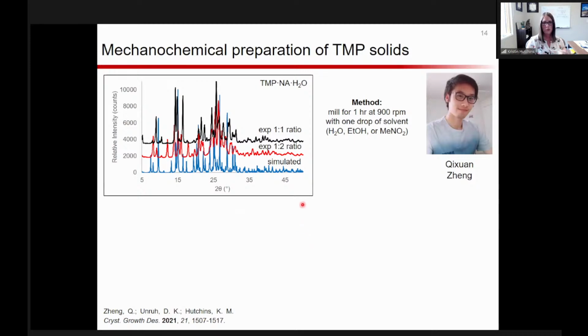With those systems, we had made them via solution, and since we had some really good properties, we were interested in whether we could make them via mechanochemistry instead. Again, we're going to do a 1-hour mill at 900 RPM, and we're going to use 1 drop of the solvent that is present in the crystal structure. So water, ethanol, or nitromethane. In the case of nicotinic acid with water, the simulated powder pattern is here at the bottom, and we did use a couple different experimental ratios. We didn't do a huge optimization, but we really didn't see excellent correlation to the simulated pattern as much as we would have liked to. So maybe some correlation, but still not what I would say is pure phases.